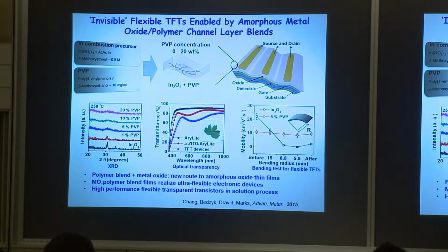Now, this is sort of interesting. Binghao Wang got the idea. We were thinking if you could incorporate a polymer into these oxide films, maybe they would be even more flexible. And so he's using here polyvinyl phenol. You can see from the X-ray that curing at 250 C, the stuff is still quite amorphous. This is the theta 2 theta scan. The films are optically transparent. There's a leaf. I hope to goodness it's not a marijuana leaf. I don't know what the students used there.